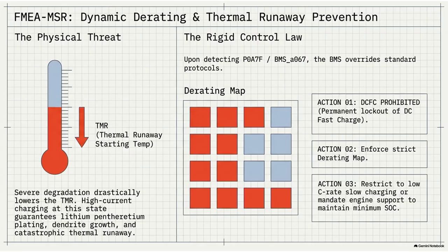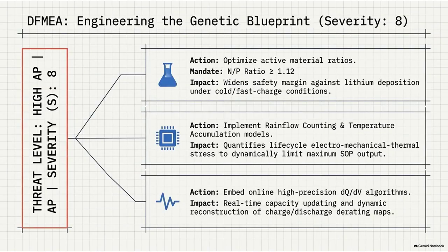Like we just discussed, cold temperatures or fast charging rates cause lithium to back up at the anode surface because the intercalation kinetics slow down. Think of it like a parking lot. By oversizing the anode by 12%, you are vastly increasing the total surface area and the sheer number of parking spaces available. So even when the chemical kinetics are sluggish and ions are backing up like cars at a toll booth, the massive surplus of spaces ensures the lithium always has a structural void to drop into. Right, which prevents surface reduction and dendrite formation. The 1.12 ratio guarantees that over a projected 10-year lifespan, even as the SEI layer thickens and consumes space, the anode maintains enough buffer volume to accept fast-charging currents without initiating plating. It is a raw, physical margin of error woven directly into the chemistry.